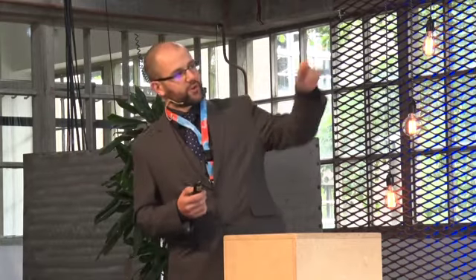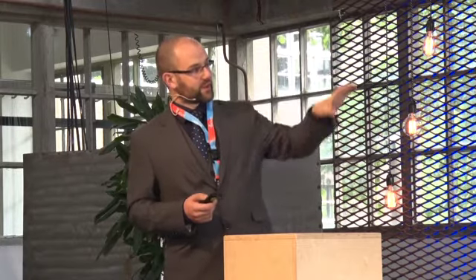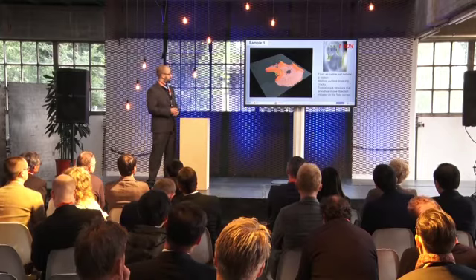The green corresponds to the yellow on the surface of that rail, so that will give you an idea of how what you see on the surface corresponds to what's underneath, and the deepest points are generally in the middle of the running band, but I believe the initiation took place where the Y-shaped crack was on the field side.